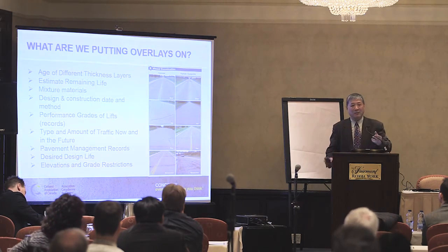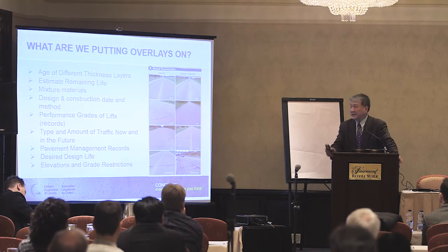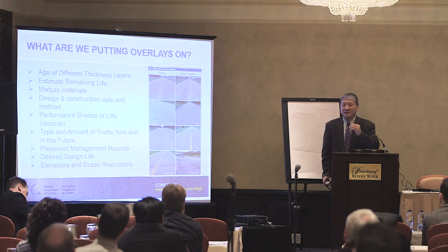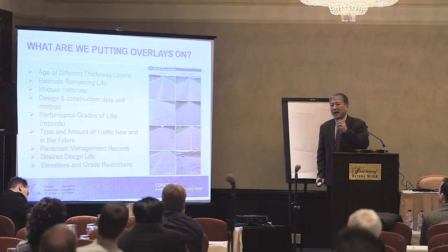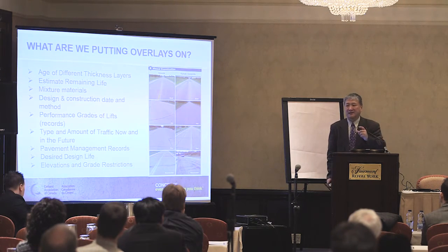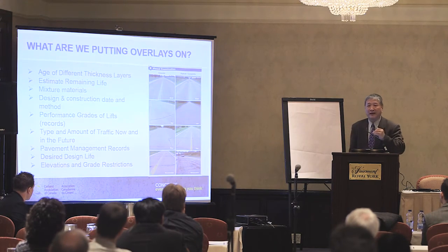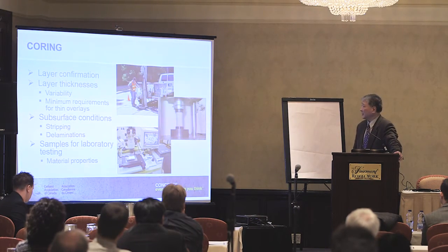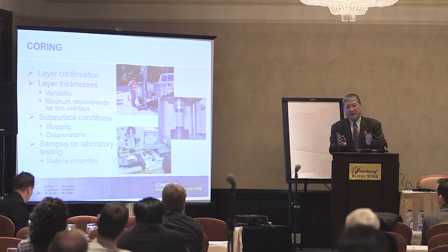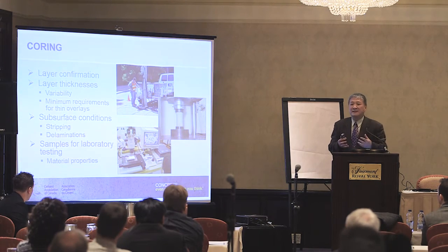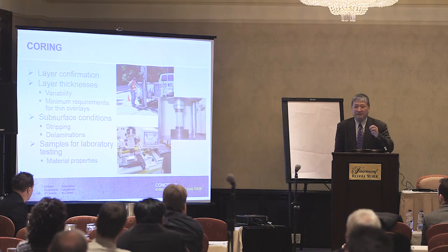If you're putting a concrete overlay on existing asphalt, you need to understand how many lifts of asphalt are underneath. After milling off all the deteriorated asphalt, you still need to maintain a minimum thickness of about 75 mm of good asphalt in place before applying any concrete overlay, whether bonded or unbonded. Your pavement management system can help review distress history, but field verification is always needed.